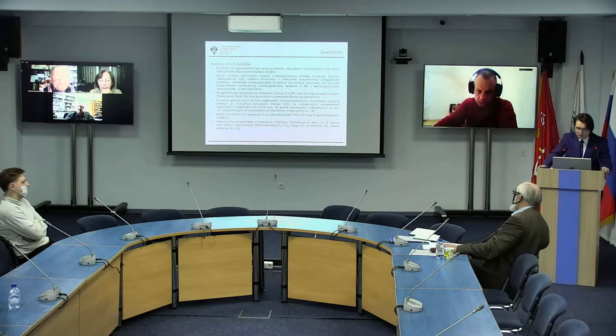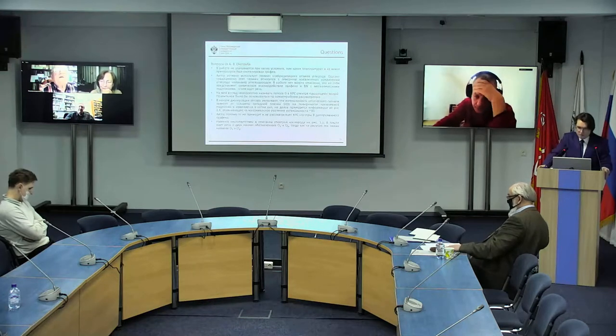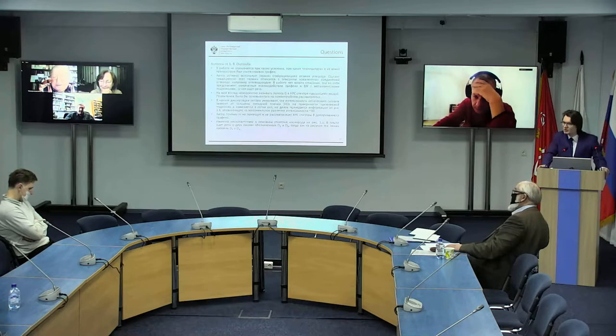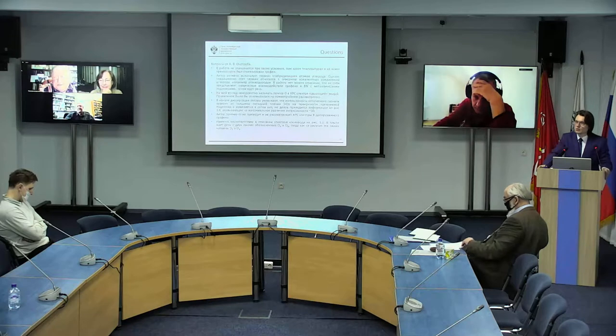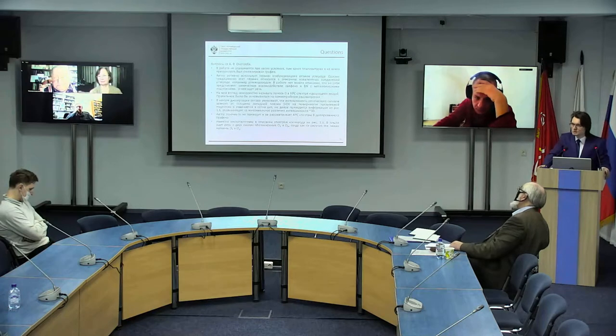As for this term hybridization of carbon atoms, I agree with that as well. Maybe that is a kind of jargon for this field. And here I referred to the strong bond between graphene and metallic substrates as a result of partial mixing of electron states of graphene and cobalt and nickel in this case.